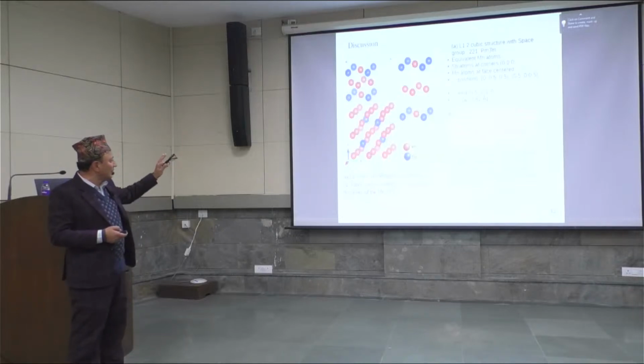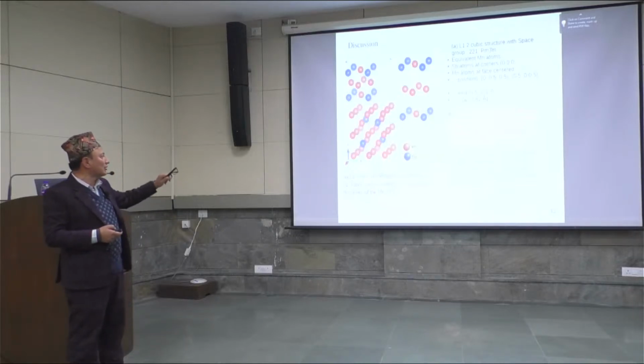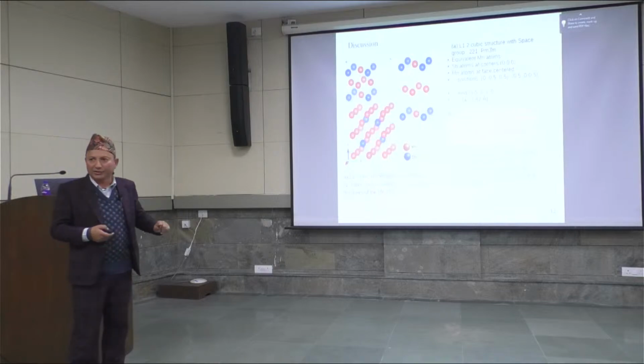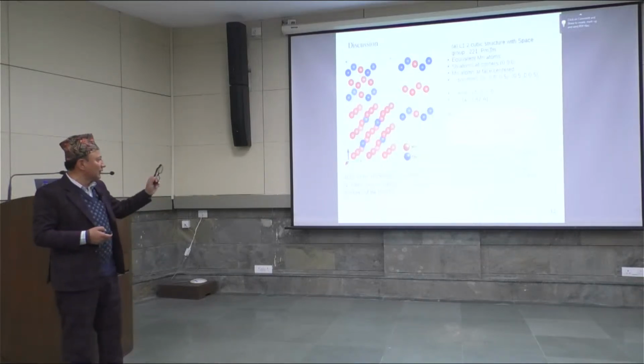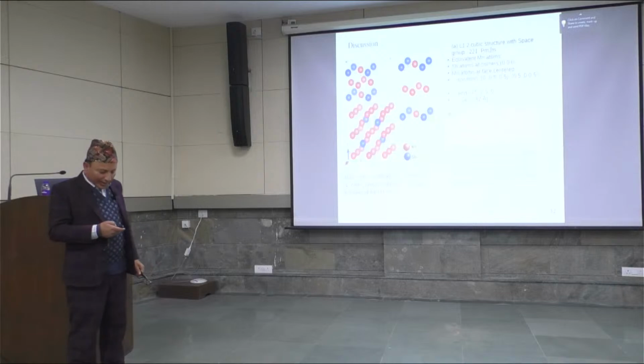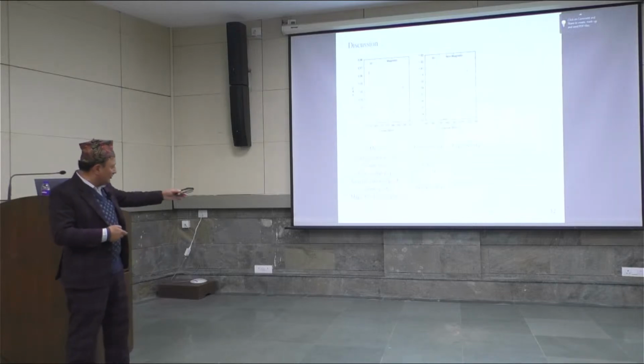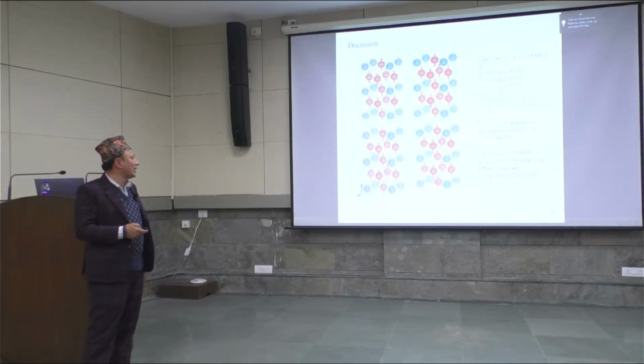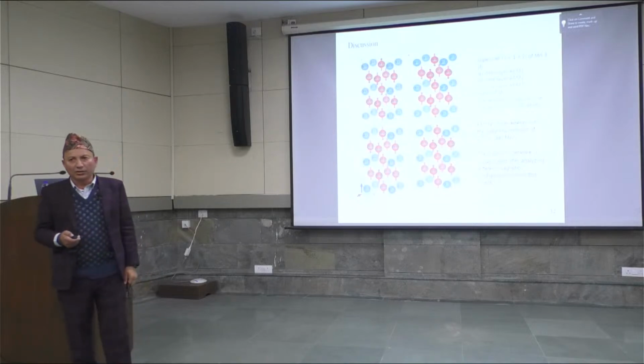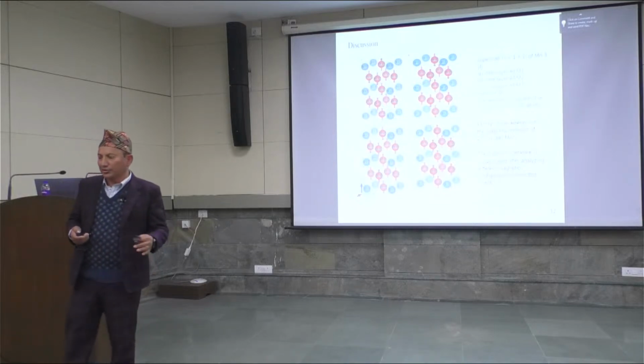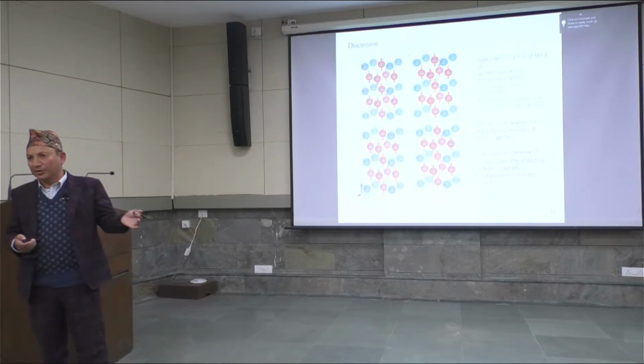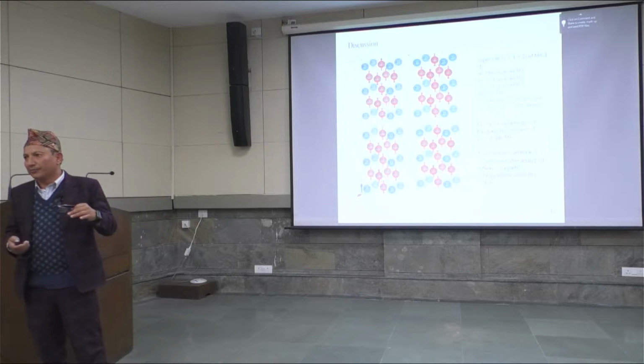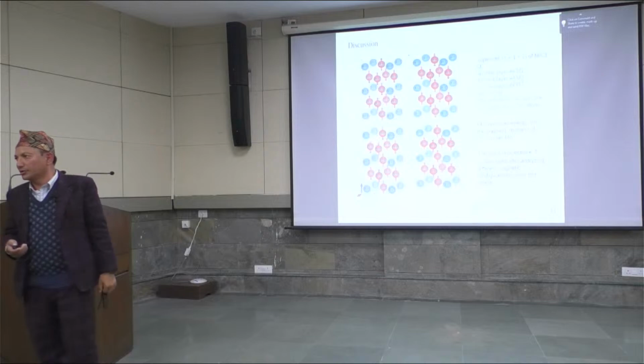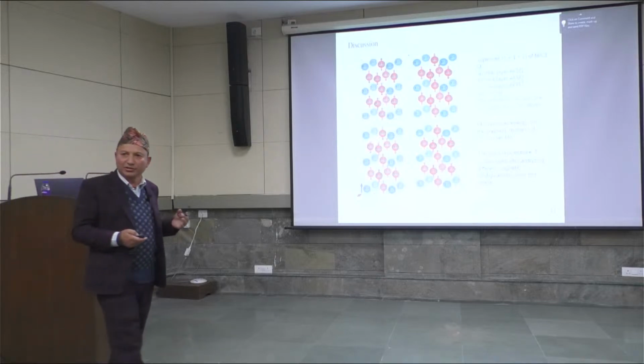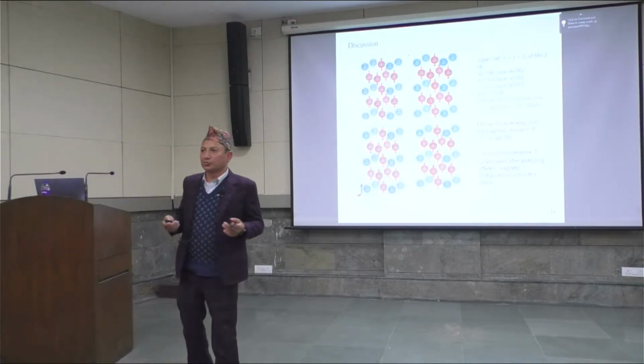The first is the L10 type structure, the second one is the distorted tetragonal structure, and the third one is the DO3 type structure. And we find that the ferromagnetic ordering is the most stable one. Then why does this happen? The neutron diffraction method gives the ferromagnetic ordering, and our calculation also always shows the ferromagnetic ordering is the most stable one. So we became interested to work on it.